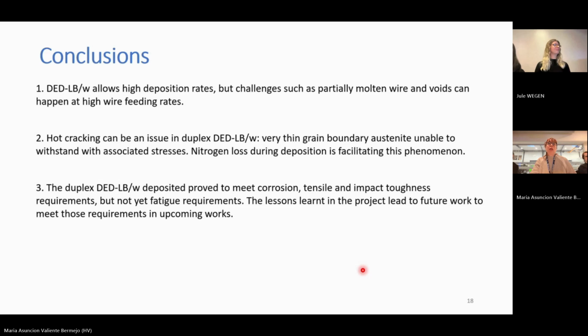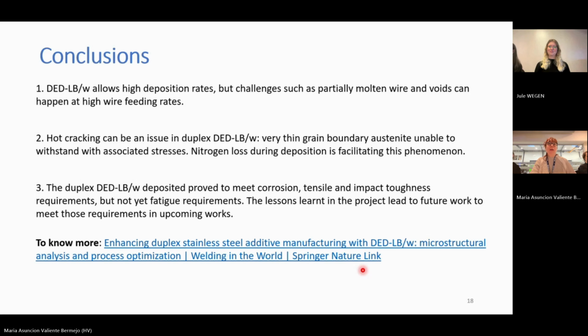And the last conclusion is that we proved with this test that this deposited material met the corrosion, tensile, and impact toughness requirements, but not the fatigue requirements. So I haven't shown you any result where the material was not meeting these fatigue requirements. The lessons learned in this project might lead to future work, and hopefully in the future meet these fatigue requirements too. And if you want to know more, there is already a paper published in Welding in the World by Springer, so you can read more if you are interested to dig deeper into the microstructural aspects.